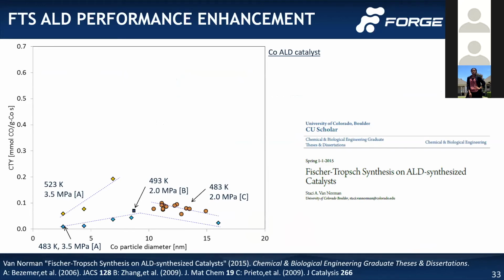Background on Fischer-Tropsch synthesis: it is a structure-sensitive reaction. It takes carbon monoxide and hydrogen and makes synthetic oil. If you look at the conversion of carbon monoxide per amount of cobalt, you have a peak around 7 to 10 nanometers on everything that has been shown for the last 100 years of research in Fischer-Tropsch.